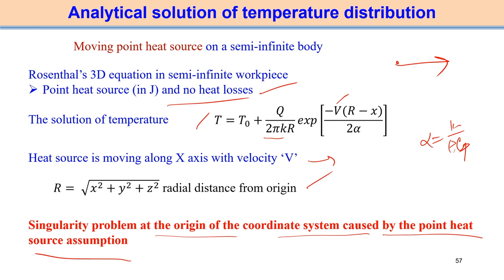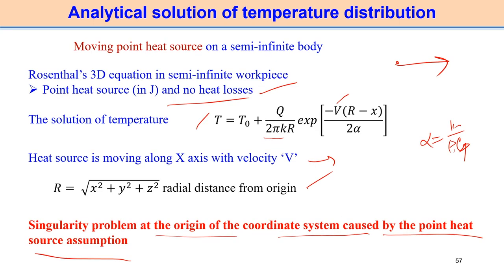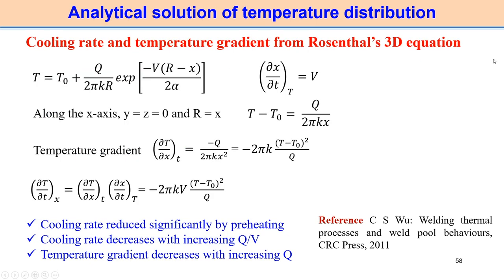From the Rosenthal's 3D equation solution, we can reach some conclusions. We can estimate cooling rate and temperature gradient, which are relevant to understanding solidification behavior and microstructure associated with the welding process. From the temperature distribution as a function of position, we can estimate cooling rate and temperature gradient. Although this solution is a steady-state solution — not a function of time — we can still use it to estimate these two components.